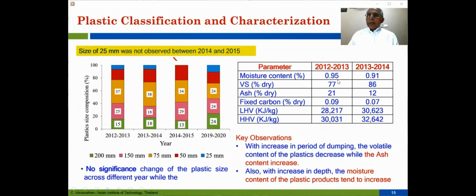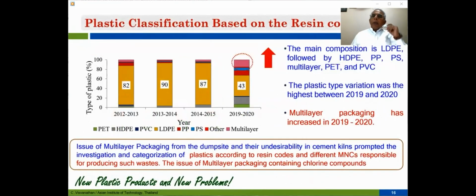And we also looked at moisture contents, okay, and the calorific value. The key observation is that with increase in the period of dumping, the volatile content of the plastic eventually decreases, which is quite normal because the organic fraction gets degraded, etc. So now we can look at the next part, plastic classification based on the resin code, between the different years, between 2012 and 2019.